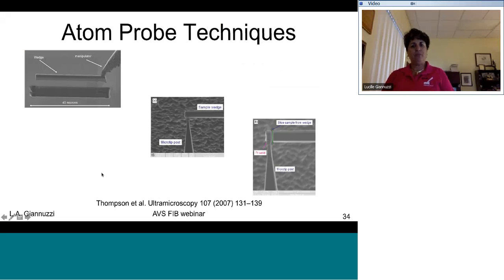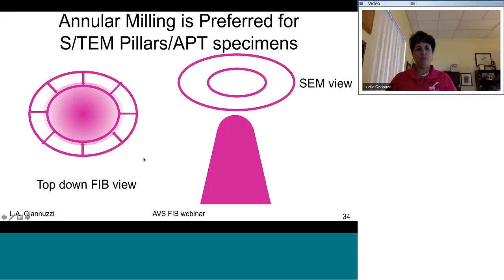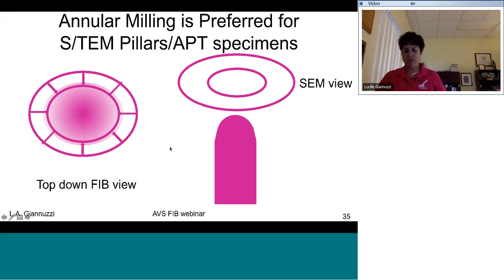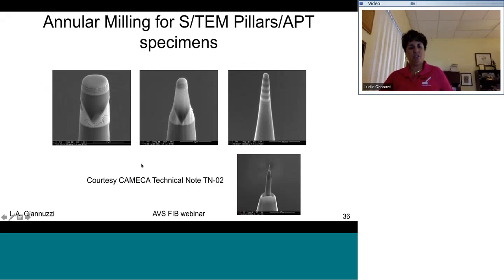Okay, atom probe techniques basically consist of lifting out a big sample, long sample, I should say, taking the end of the sample, putting it on this microchip or just a TEM grid itself, cutting it, attaching it, and then cutting it free, and then you've got still all this length of sample and then some to go and put multiple samples on multiple tips, and then you do annular milling now to subsequently get the sample thinner and thinner. And as you get it thinner and thinner, then you also have to use your low energy polishing, again, which I'll describe later. But this is an example from the technical note showing a bit of sample lifted out onto a microchip, and then the process of going thinner and thinner.